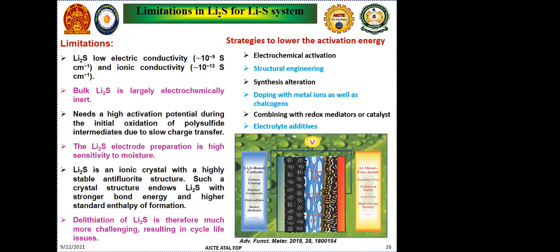So with electrochemically inert Li2S, we are not going to get proper charge-discharge or well potential. So we have to think of how to make the Li2S electrochemically active. Apart from that, the activation energy of Li2S is very high. So even though we can activate the Li2S, we have to spend a lot of potential to activate this.